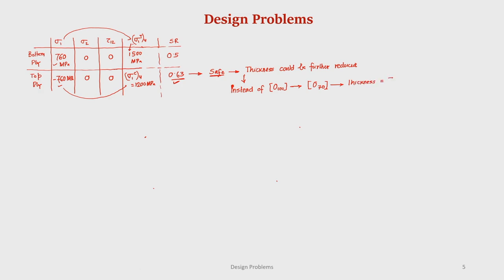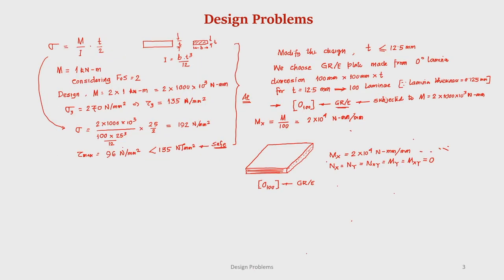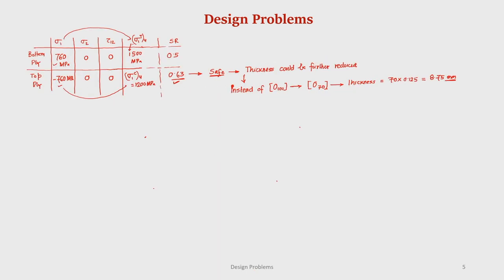thickness will be 70 into 0.125, this comes out to be 8.75 mm. Okay. So, we can see that 70 layers of graphite epoxy, which translates to a thickness of 8.75, which is much less than the half of the thickness of the aluminum plate, would suffice. You can still do the analysis and see that it is safe.